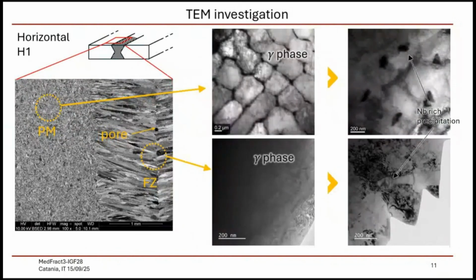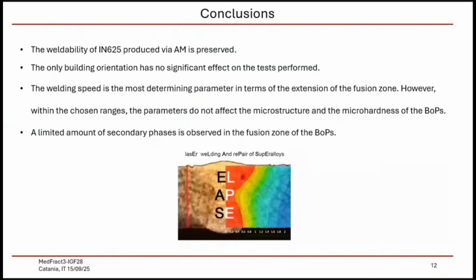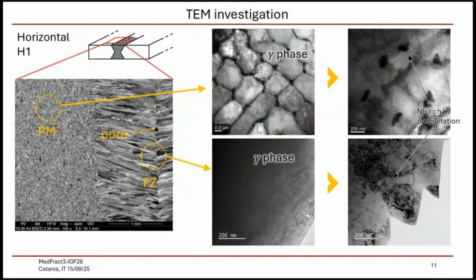So we decided to investigate these phases more deeply with a TEM investigation. As you can see in this schematic, the samples were taken from the horizontal plate from the top surface, including also the fusion zone of the first BOP. So we have two samples, one from the parent material and one from the fusion zone. In the parent material, we found the typical cellular structure. It's typical of additive manufacturing components. But this structure is completely removed in the fusion zone because the welding process completely reset the microstructure.